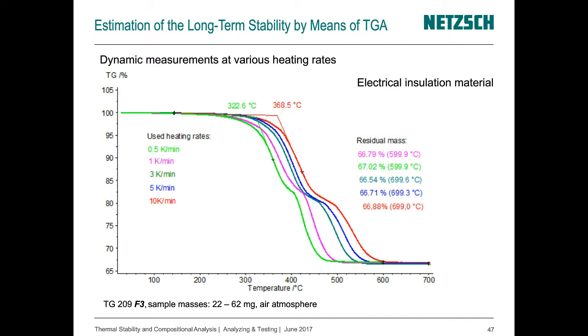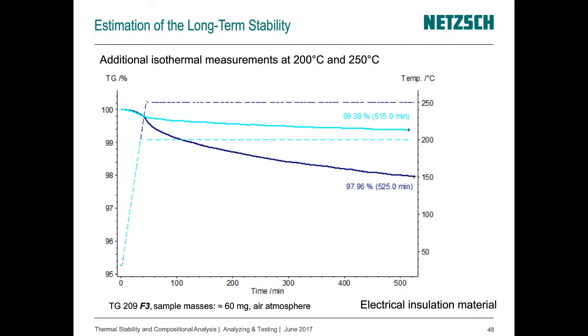The profiles of the measurement curves are more or less the same, so not changing much. And the total mass loss is also more or less the same. The organic content is about 33%. But if we are intending to make long-term predictions, it's always advantageous to have not only dynamic measurements, but also some isothermal measurements included. And two of the isothermal measurements you can see here.